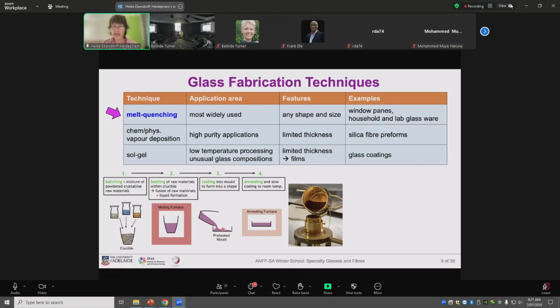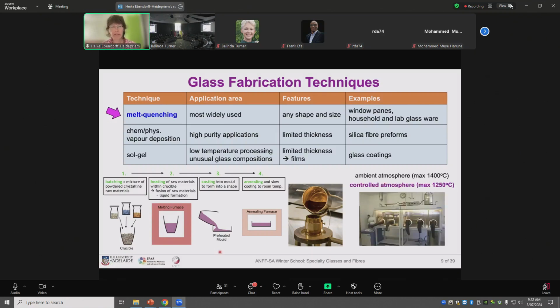Then the trick here is that the glass cools down quickly, therefore quenching from the melting temperature to the glass transition temperature, where the glass is hot but solid. And because of this quick quenching, the atoms don't have enough time to move around so that they can form crystals. Now then the hot but solid glass goes into an annealing furnace, cools down slowly to room temperature to avoid crystallization. And here you see a photograph of a gold crucible. You see here a telluride glass melt, which is cast into a cylindrical brass mold. And at Optofab Adelaide, we have facilities for melting at ambient atmosphere and at controlled atmosphere.